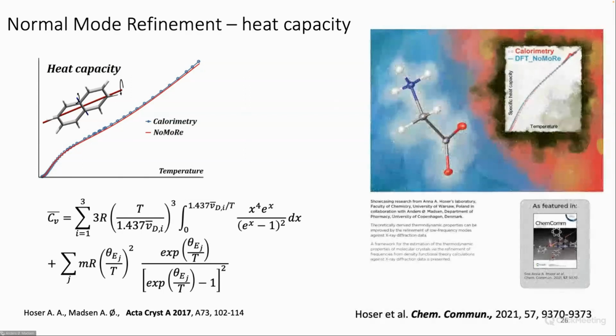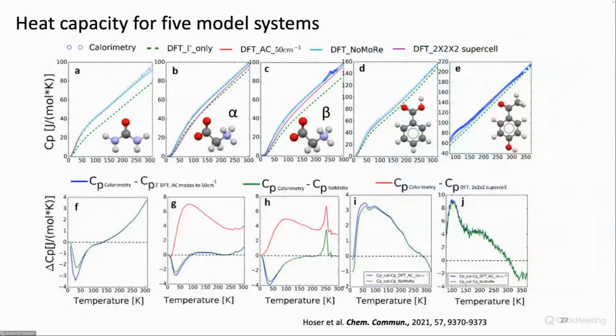Actually, Anna Hoser has performed quite a range of such studies of measurements and comparisons of heat capacities between calorimetric measurements and these normal mode derived, or dynamic quantum crystallography derived, heat capacities. And here's the summary of that. You can see for many of these small molecules, we actually have quite a good agreement.